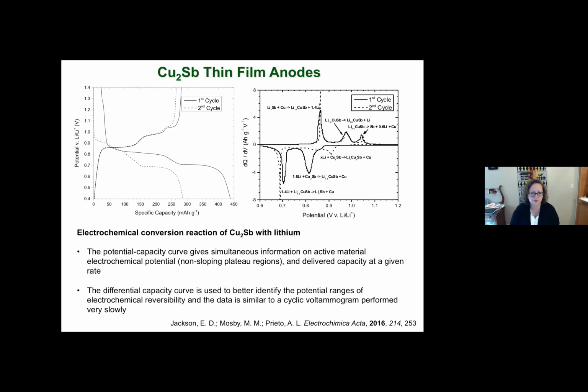On the left, I'm showing you a plot of the potential versus lithium, Li+, on the y-axis, versus specific capacity on the x-axis. The first cycle is the solid line, and the dotted cycle is the second cycle. What I want you to get from this is there's actually a pretty significant irreversible capacity loss on the first cycle. There are also multiple plateaus, which tells you that there are intermediate phases that are accessible.